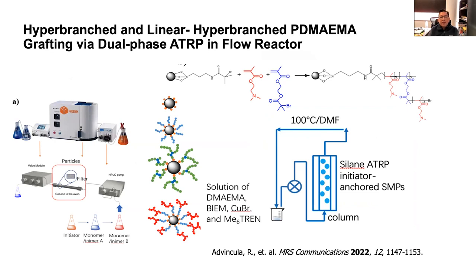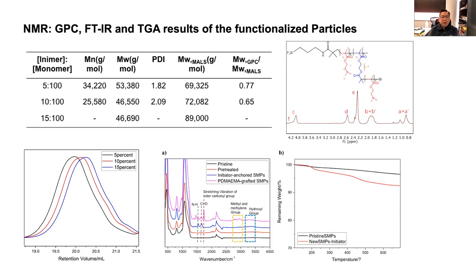In this case, an inimer was used, where the inimer, or initiator monomer, facilitated the reaction of this DMAEMA monomer, resulting in a saturated amine group present on the surface in a hyperbranched form, as shown schematically here. And the same sequence was done by packing the particle with an ATRP initiator this time, and then controlling the ratio between the monomer and the inimer, and also the residence time.